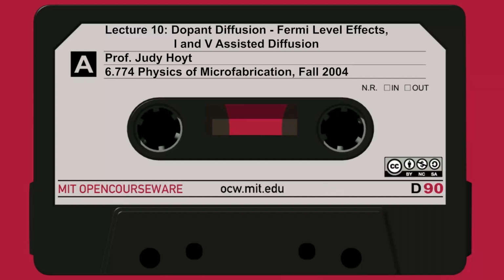In Table 7.3, you were given this exponential dependence. The activation energy, averaged out, was 3.99, and the pre-exponential was 9.17. When you calculate that at 1,000 degrees, you get about 1.48 times 10 to the minus 15th, very, very close. So as a sanity check, this two-term model is not screwing up your intrinsic diffusion coefficient. You're getting exactly what you would have gotten with the simpler table and the simpler calculation in Table 7-3.